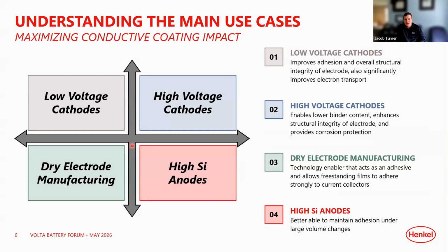So with that, it brings me to understanding some of the main use cases of conductive coatings. This little matrix, we'll talk through it, and then I'll highlight a couple of them too. The advantages that conductive coatings bring are dependent on the materials being used and the manufacturing process being done. When we look at low voltage cathodes, something like LFP, maybe done traditionally with NMP slurry application, what the conductive coatings do here is certainly improve adhesion and the overall structural integrity of an electrode, but you're really getting an enhancement of improved electron transport across this electrode. It really enhances the overall conductivity, and gets rid of some points of high resistance that are typically found within LFP cathodes.